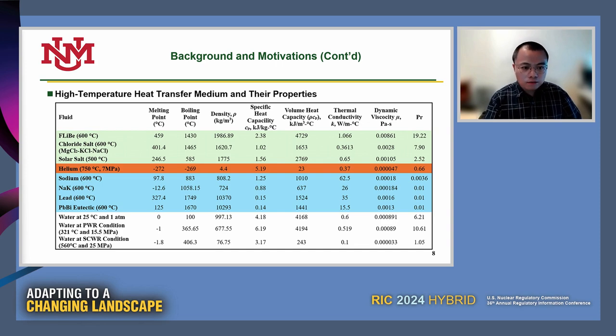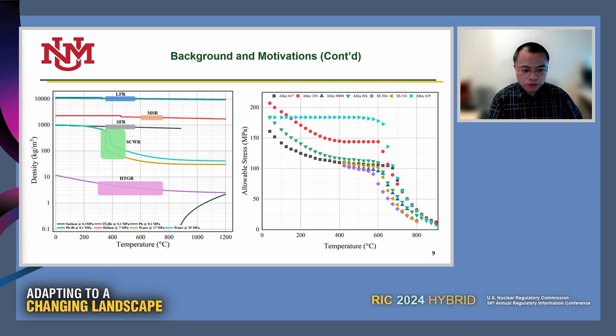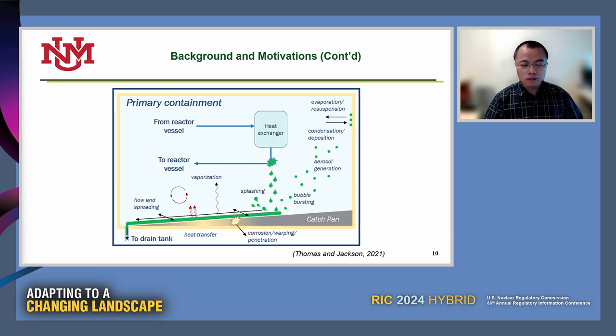But then we move to the next slide, where we made a drawing of density with temperature. From the left figure, you can see only the molten salt reactor and the high temperature gas-cooled reactor can operate at more than 600 Celsius. The figure on the right shows the allowable stress for different materials with temperature. As you can see, above 600 Celsius, the allowable stress dramatically reduces, which means high temperature, high or moderate pressure systems require advanced metals. Sometimes advanced metals are very challenging, and it's also possible that they are not code-certified. So the takeaway message is that the molten salt reactor advantage is operating at very high temperature and low pressure. Next slide, the topic: molten salt spill.